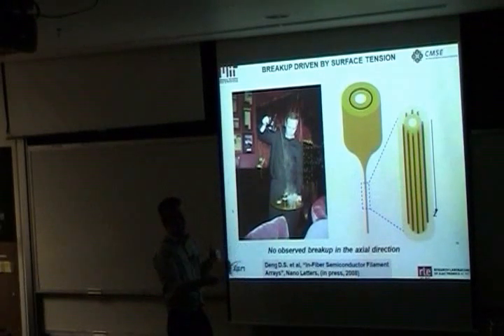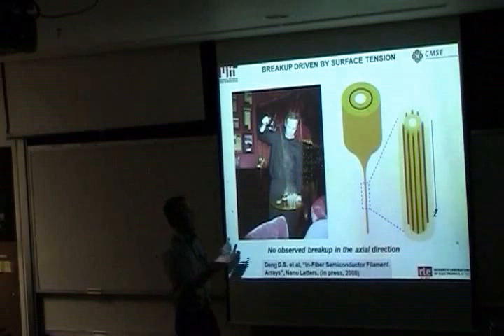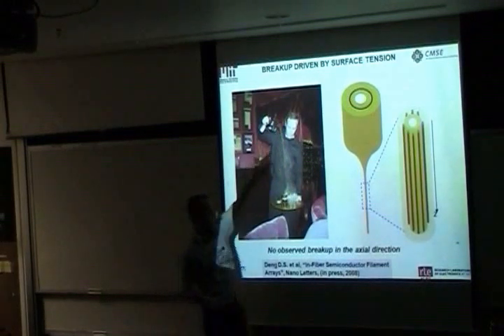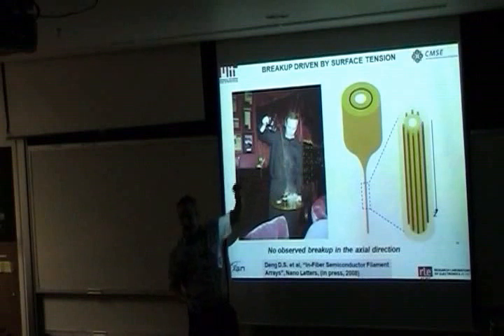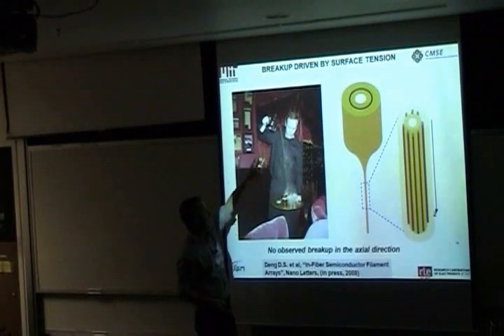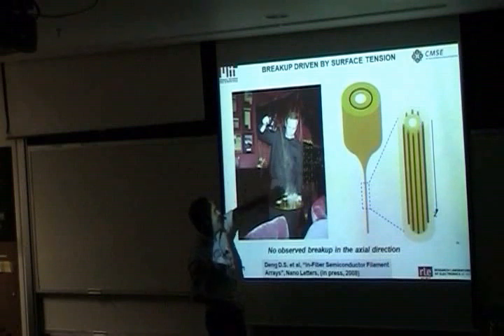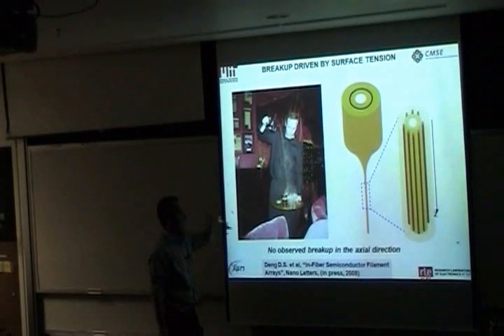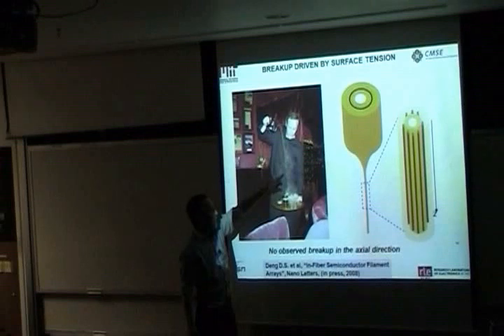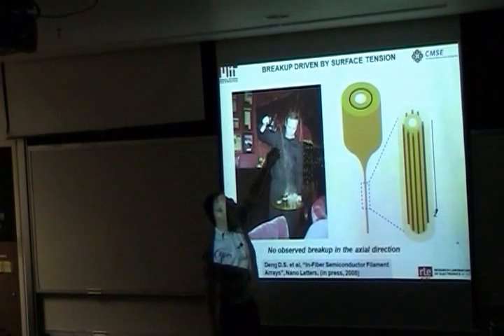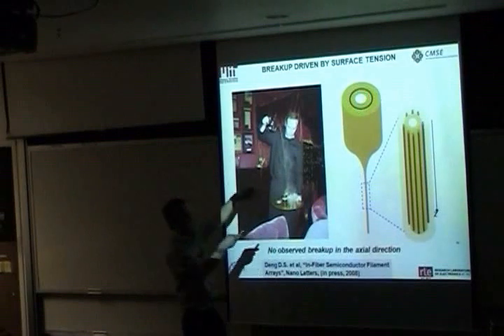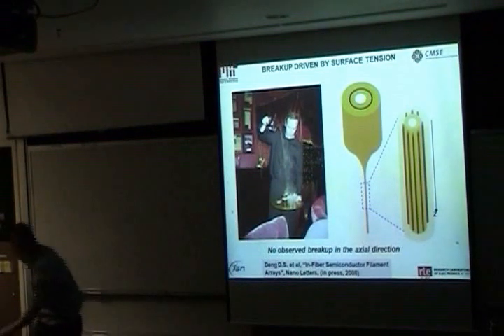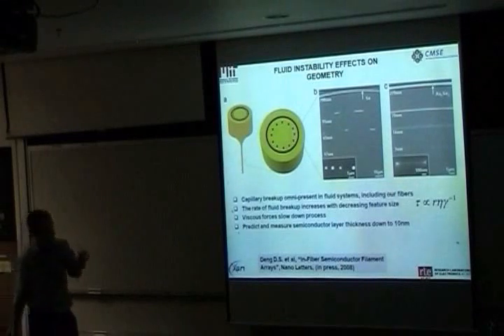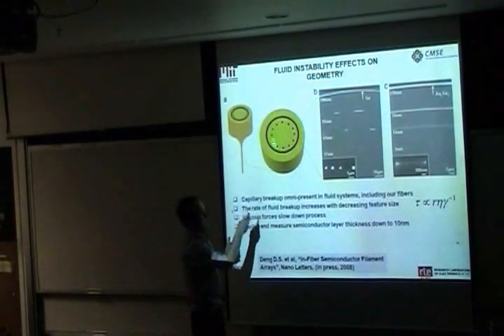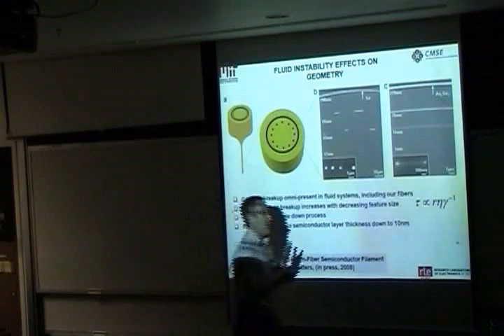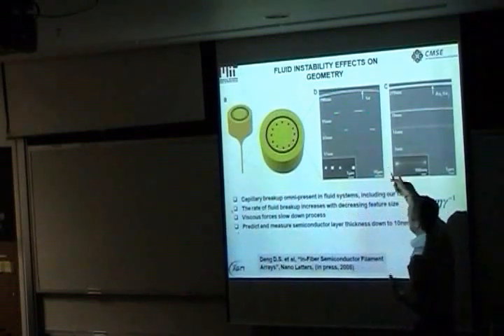And these fine cylinders are coming about because of a process which is not that different from a capillary breakup process, which happens when you take a little tea kettle and you pour it from some height. This is a little Moroccan restaurant in Charleston near where we are. And you can see that obviously the tea cylinder is breaking into spheres. In this case, there's a layer that is breaking into cylinders. It's a two-dimensional version of this. And it actually turns out that you could get this kind of breakup or not get it at all, and it really depends on a number of things.